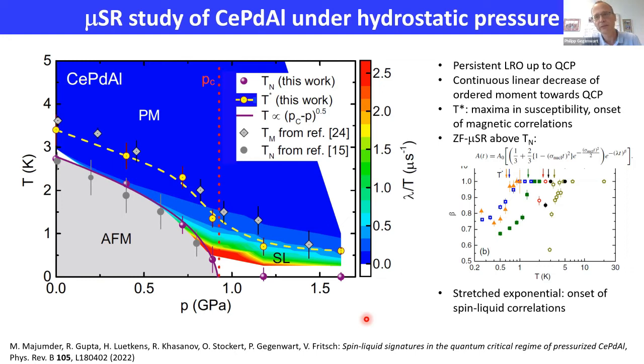And interestingly, we found that the onset of this stretched exponential behavior agrees very well with the T* maximum that is detected from the magnetic susceptibility under pressure. So this line defines the onset of the spin-liquid correlations. And then we also tried to look for indications of non-Fermi-liquid behavior and quantum criticality in this pressure regime.